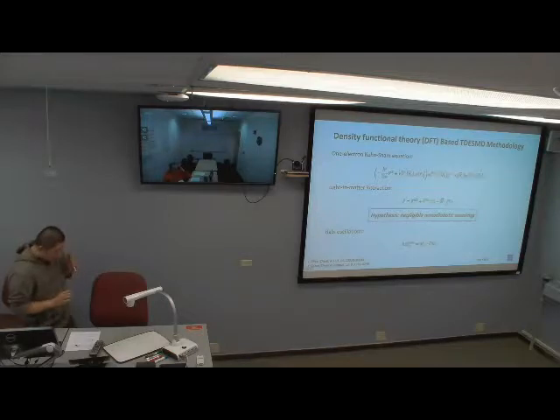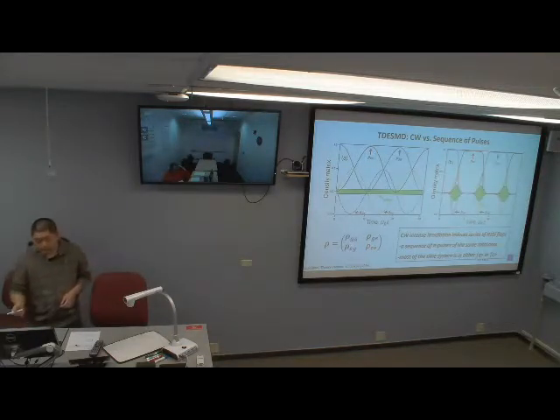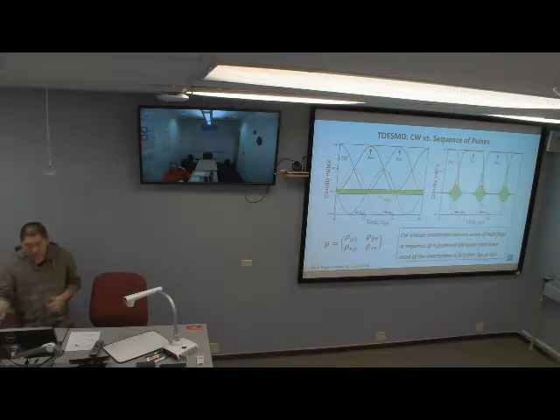And here we hypothesize that the non-adiabatic coupling is negligible. This is because the probability of electronic transitions induced by photons is much higher than the probability of electronic transitions induced by phonons. So the presence of laser field induces rapid oscillations between state I and state G. So the Rabi frequency is related to the transition dipole moment and also the intensity of the electric field. So the occupation of orbitals experiences a change in time due to rapid oscillations with the Rabi frequency.